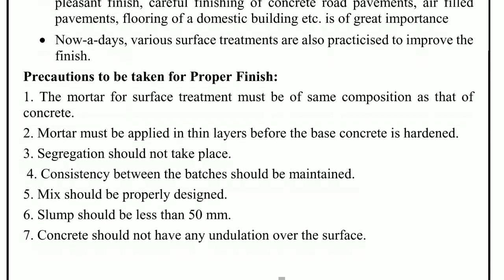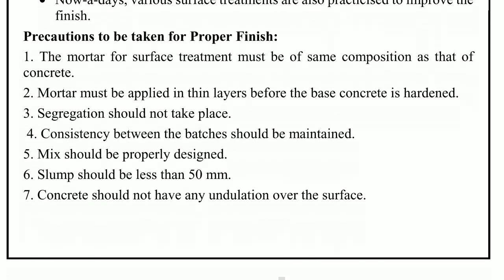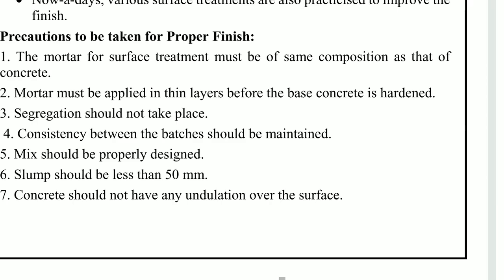Some precautions to be taken for proper finishing: the material used for surface treatment must be the same composition as that of the concrete. Mortar must be applied in thin layers before the base concrete is hardened. Segregation should not take place, and consistency between batches should be maintained. The mix should be properly designed; slump should be less than 50mm. The surface should be plain, level, and smooth.